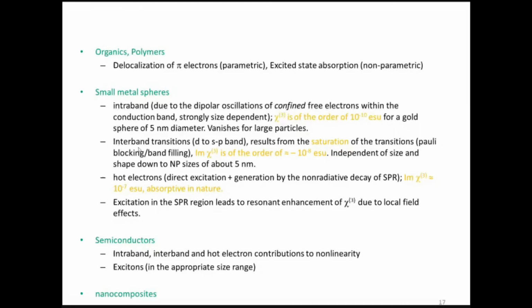Now, the other type is interband transitions. These are the d band to sp band transitions. Again, all this we are talking for nanoparticles. That's very important. Because if you talk about bulk metal, then these bands also will be mixed up. So here, there can be absorption saturation because of Pauli blocking, and the chi3 here is of the order of 10 to the power minus 9 ESU. This is actually the imaginary part of chi3, which corresponds to absorption or amplification.